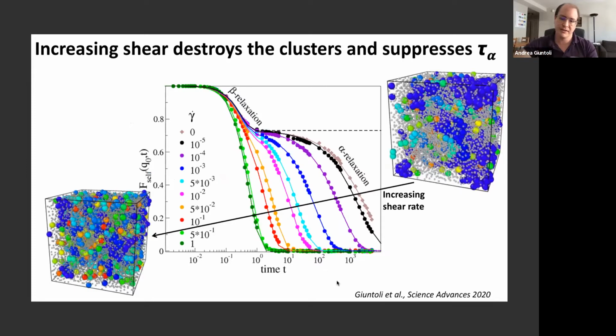We started playing with our polymer model, and you can measure the intermediate scattering function, this brown line at equilibrium, that has the two relaxations. And you can see these clusters of immobile particles standing there. And then you start applying shear to the system. And the more you do that, the more you suppress the alpha relaxation. And the reason for that is that you are destroying these clusters, and you reach a point where the system is much more homogeneous and equally distributed. And you can see this in the intermediate scattering function, because at some point you're only left with a single relaxation, and the second long alpha relaxation is gone.